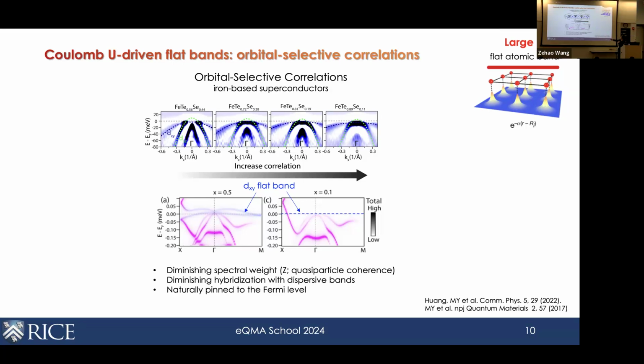And also what this indicates is that the effective mass of that XY orbital becomes heavier and heavier as you go towards this end. So what we're really seeing here is that this correlation effect is orbital dependent. Because if you look at the other orbitals here, their bandwidth or their slope or their effective mass don't really change as you go from one to the other.